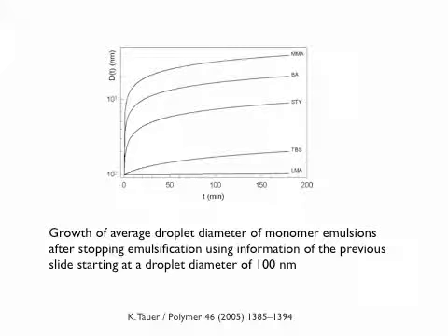So this would mean that if this would be the case, this would severely limit my application of mini emulsions, right? Because I can only do it for very hydrophobic components if water is my medium, my dispersion medium, which means that my brilliant idea of making mini emulsions of everything would completely fall apart, and it would be a technique that can only be used for a very restricted amount of materials.